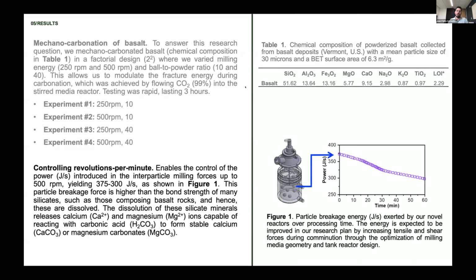Now, the first result that I want to show you is how the power is actually changing in the first hour of mechanical carbonation. What you can see here is that the power in joules per second is actually decreasing as we progress during this mechanical carbonation. The reason why I wanted to show you this first is that this is a really important key takeaway of the technology itself: as we mill, we're breaking apart the basaltic rock and fluidizing our reactor so that it consumes less power over time. This is really important when we're thinking about life cycle analysis and techno-economic analysis to make sure that this technology has the maximum benefit to decarbonizing the concrete sector.